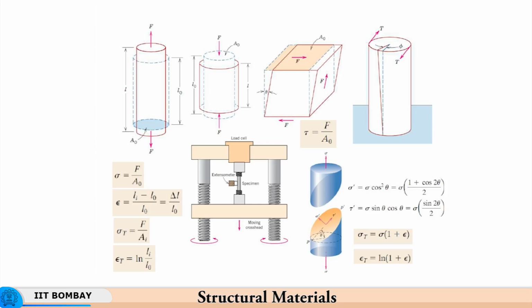On this plane also I have to find the perpendicular component. So, that is F cos theta, which is the perpendicular component of force, and this area is A divided by cos theta. So, now I have the expression F cos theta divided by A by cos theta, and that gives us the value sigma cos square theta, right. And based on our trigonometric relationships, we can also write this as sigma times (1 plus cos 2 theta) by 2.